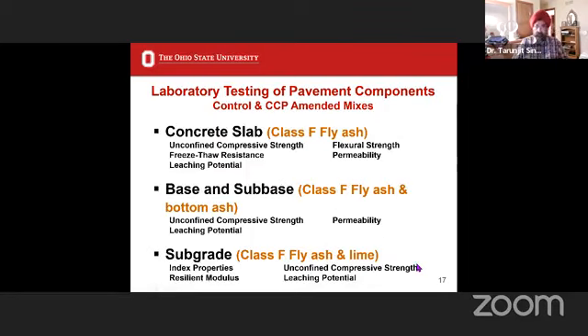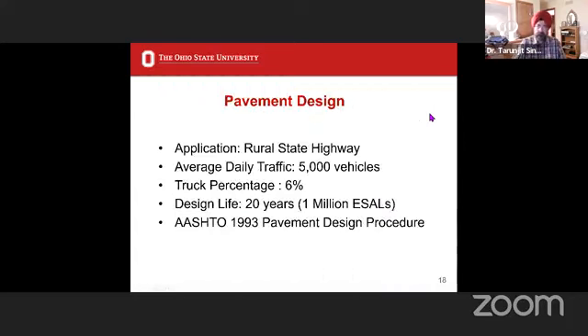And here is a summary of the different materials. In the concrete slab, we use class F fly ash. This has all the lab testing that was done before any construction was done. We have base and the subbase with fly ash and bottom ash. And the subgrade was done using class F fly ash and lime for soil stabilization. So it gives you a sense, you can see leaching potential goes through each one of them. All these lab testing had to be done before we proposed our control sections. Control means there is no coal combustion product in them, and the CCP amended sections would have.